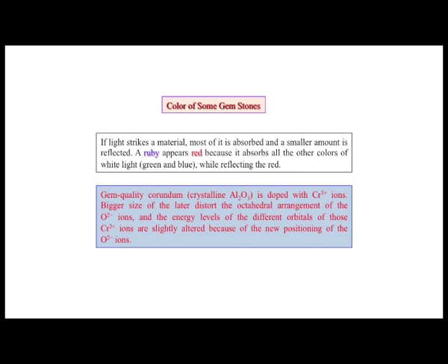All the oxides are your new ligands. So, in the solid state we can consider these O2- as our new ligands instead of water or hydroxide ion. These O2- will now be placed around the chromium 3+ and will distort the octahedral arrangement which was originally present in the alumina structure, because the chromium size is different from the aluminum size. So, doping is basically bringing some imperfection to the system, and it will slightly alter the absorption, which we do not get for the corresponding hexa-aqua chromium 3+ complex.